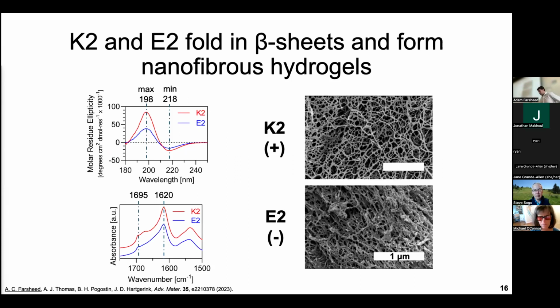And then switching over to visually looking at the nanofibers, again with scanning electron microscopy, we can zoom in to extremely high magnification. And on the top, we can see K2, and the bottom, we can see E2. And both of these form this nanofiber structure that looks kind of like a web.